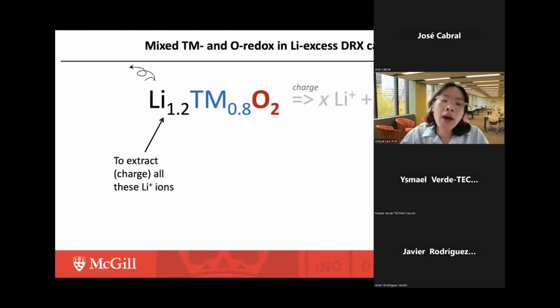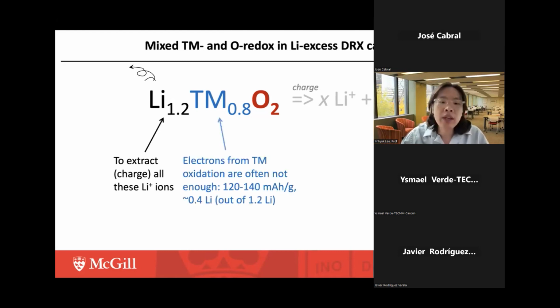But what happens is that typically the electrons coming from the transition metal oxidations are often not high enough. And typically in experiments, only 0.4 lithium out of 1.2 lithium can be extracted using the transition metal oxidation, leading to the transition metal specific capacity of around 120 to 140 milliampere hour per gram.